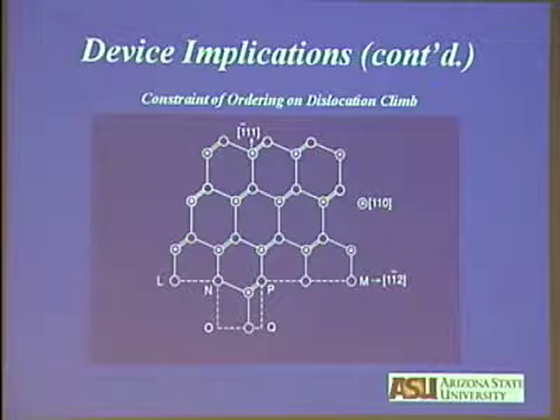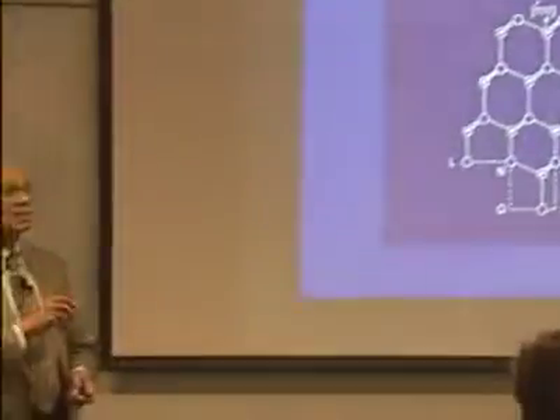The presence of phase separation will retard the multiplication of dislocations. So what it tells you, if you are dealing with light-emitting devices which degrade by the multiplication of dislocations, these things can't happen easily. You will prolong the life of your devices. And that's what you observe. Indium gallium arsenide phosphide on indium phosphide, even though it's more defective, is phase separated, and it has a much longer life than the gallium arsenide based devices, which are more perfect because they're not phase separated.